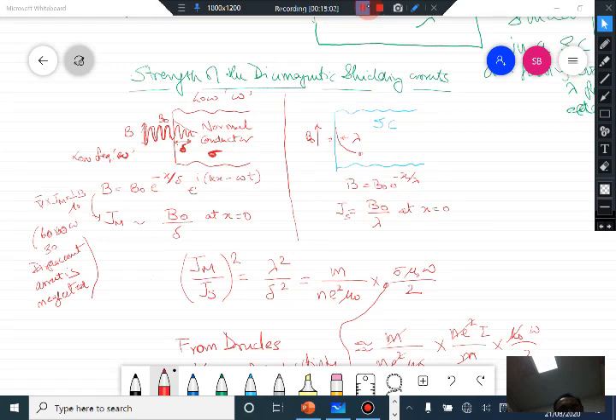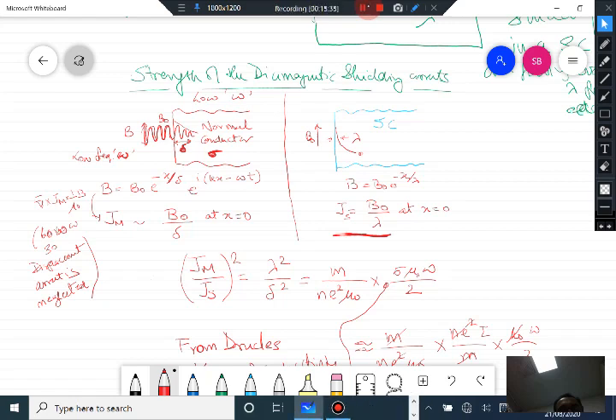The strong diamagnetic shielding currents in a superconductor screen the interior from the magnetic field. Whatever magnetic field you apply, the strong shielding currents cause it to die out within the edge of the sample, and within the superconductor it is zero. This gives rise to the lambda penetration depth for both DC and AC cases. The shielding current is of order B₀/λ, where B₀ is the strength of the magnetic field at the boundary. Now, how large is this current? Let us compare it with a normal conductor.